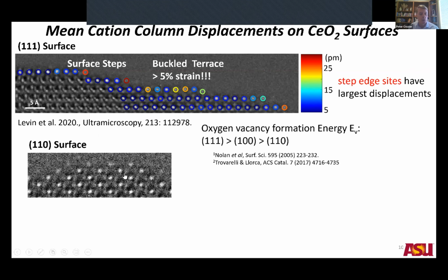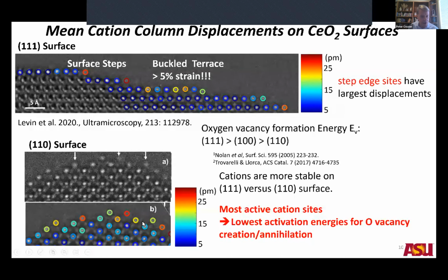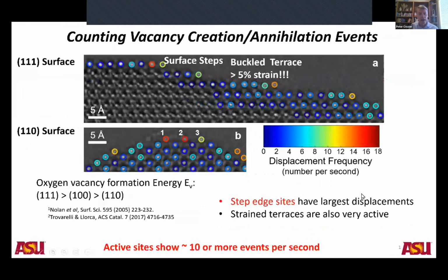And so we went over and looked at a 1,1,0 surface, and here's the movie, and you can see that along the surface, all the cation columns look fuzzy. And Ethan and Barnaby measured that, and what you find is that there's very large activity going on here. The cations are very active, and of course, the more active the cations are, that's indicative of the active site for creation and annihilation of oxygen vacancies. And in fact, because we have these direct electron detectors, we can sense structural dynamics without needing high time resolution. Of course, we can take advantage of the time resolution that we have.